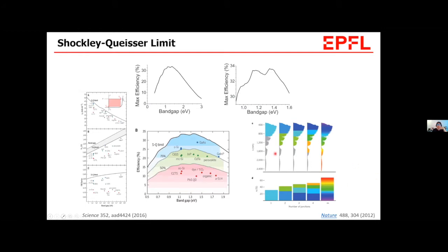Then, if you fabricate a perovskite solar cell, what would be the maximum efficiency? We should have a look at the Shockley-Queisser limit, which is the maximum theoretical efficiency of a solar cell. It takes account of the solar spectrum, and based on the calculation, I cannot present the details, the maximum efficiency is 33.7% for a solar cell with a band gap of 1.34 electron volts, if I remember correctly. So this is the limit of JSC, VOC, and fill factor as a function of the band gap of a material.